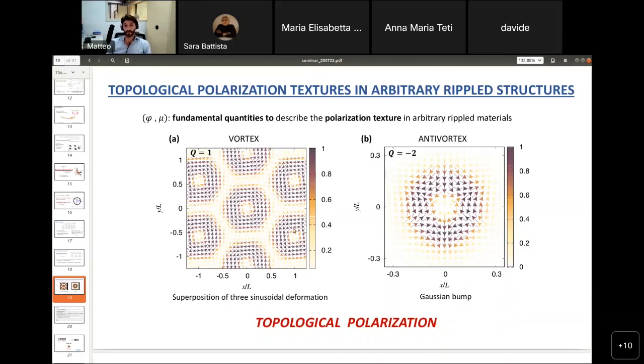Here I report, for example, two examples. The first one is a periodic deformation corresponding to the superposition of three sinusoidal deformations in turn described by three wave vectors that are rotated from each other by 120 degrees, and then the result is described by a threefold symmetry. While the second is the application of a single Gaussian bump, which means just perturbing the material at one single point by a Gaussian-like deformation.